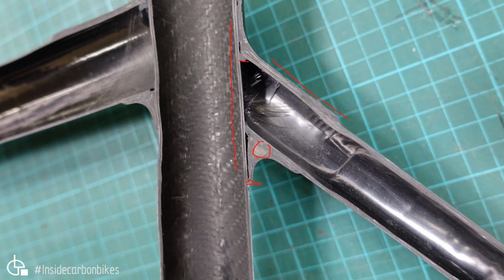There is also some delamination. You can see these lines here of the unidirectional, and that's obviously from the mitering process where maybe the cutter wasn't sharp enough. It was maybe a little bit dull, and you get a little bit of fibre tear out in that space.